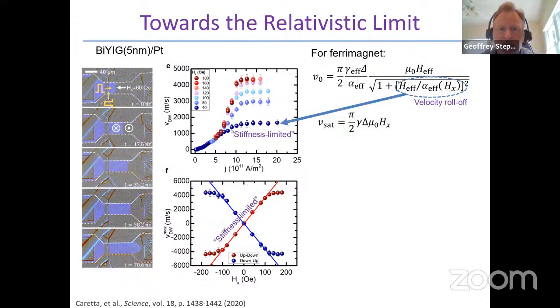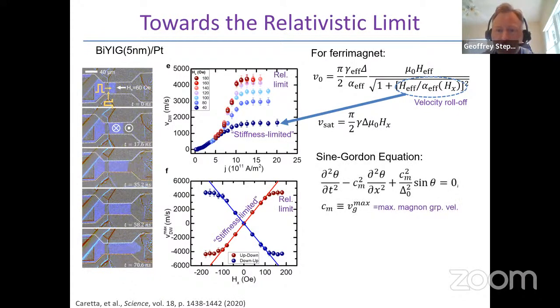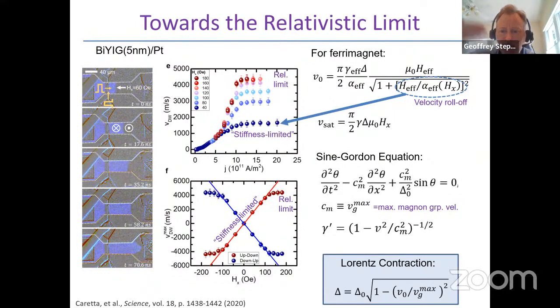So in these materials, we've gone from this conventional domain wall dynamics, where it is stiffness limited, to this relativistic-like domain wall dynamics, where what essentially happens is the domain wall velocity is always proportional to the domain wall width. As you drive it faster and faster, Lorentz contraction will increasingly decrease the domain wall width, so that gamma delta over alpha, which is the mobility of the wall, will go down as the velocity goes up, and that limits the velocity to the maximum magnon group velocity.